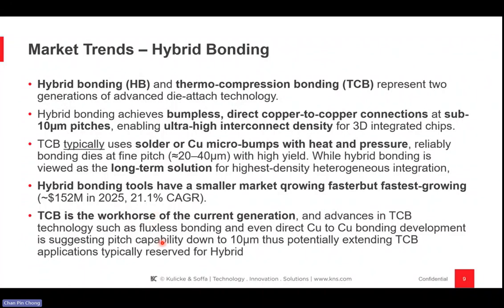TCB, thermal compression bonding, is the workhorse of the current generation, and advances in TCB technology such as fluxless bonding and even direct copper-to-copper bonding is now suggesting pitch capability down to 10 micron, and thus potentially extending TCB applications typically reserved for hybrid bond. Right. So we would discuss some of this in the subsequent slides, the difference between hybrid bonding versus thermal compression bonding, because thermal compression bonding is the workhorse right now for most of the devices at 20 to 40 microns. As the pitch gets down to sub 10 microns, there'll be a flavor of mix between TCB versus hybrid bonding, depending on the package type and package density and package height, and a lot of different applications.